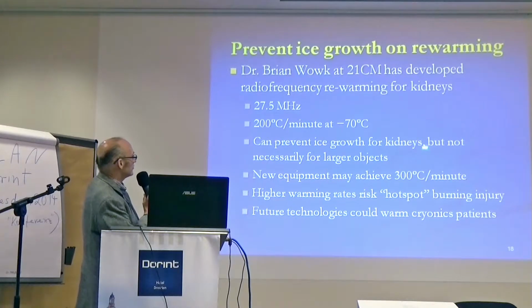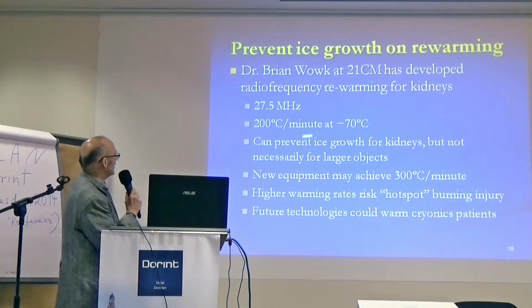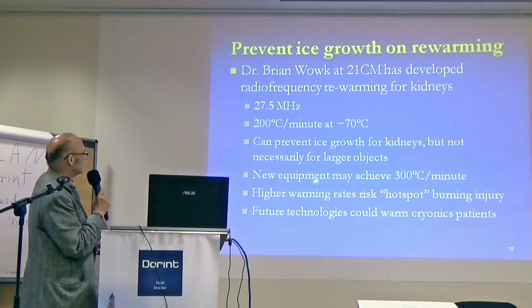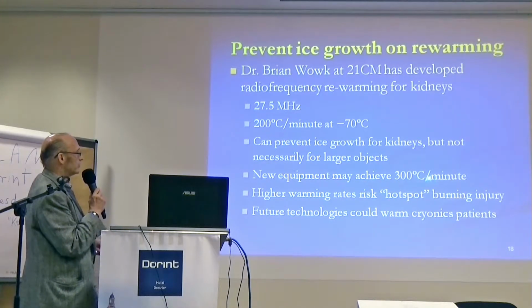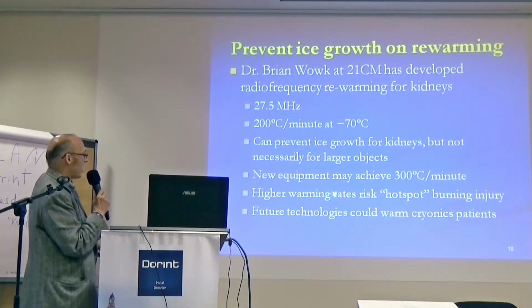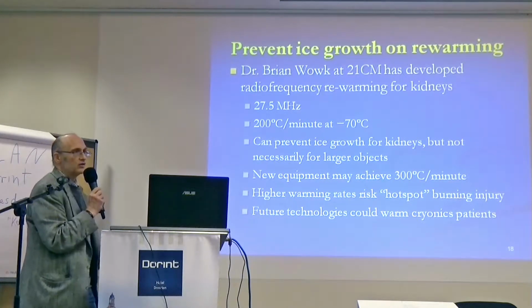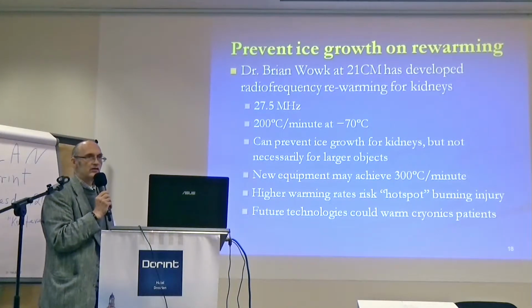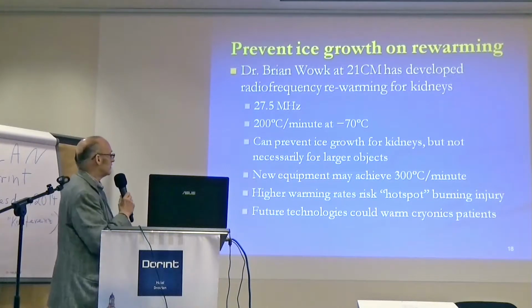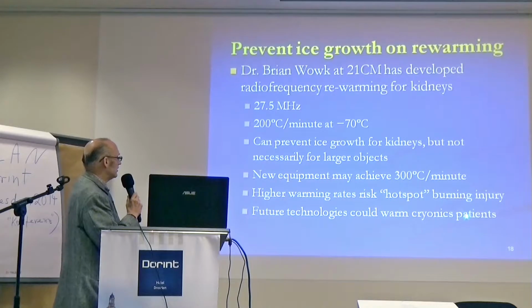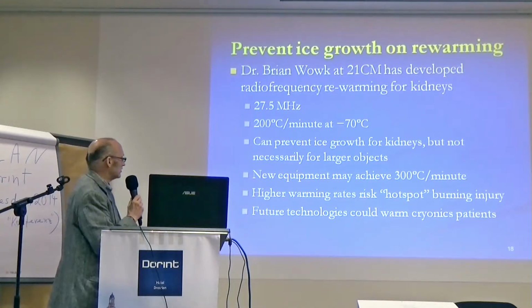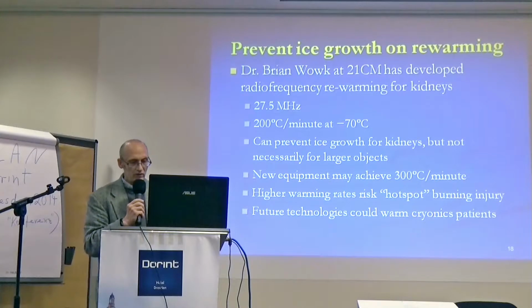So we can prevent the ice growth in kidneys, at least for kidneys, at 200 degrees Celsius per minute, not necessarily for larger objects at this warming rate. But it's possible new equipment could achieve 300 degrees Celsius per minute. But the higher warming rates risk hot spots. We don't want to burn the tissues, and there's a risk of burning tissues if you heat too quickly. Maybe future warming technologies will overcome this. That remains to be seen.